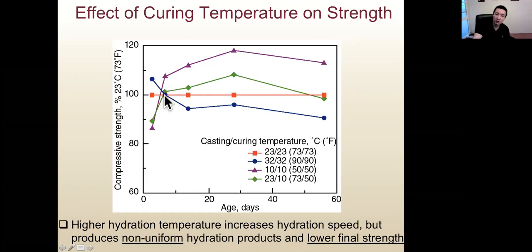When we reduce temperature, the early age strength will be lower because we have slower hydration speed. At early age, we have less hydration product such as CSH, so the strength will be lower. But the final strength tends to be higher compared with the control mix and also the concrete cured at high temperature. Same reason, with slower hydration speed due to lower temperature, we have more uniform hydration product, so the final strength will be higher. This is the effect of curing temperature on the strength of concrete.